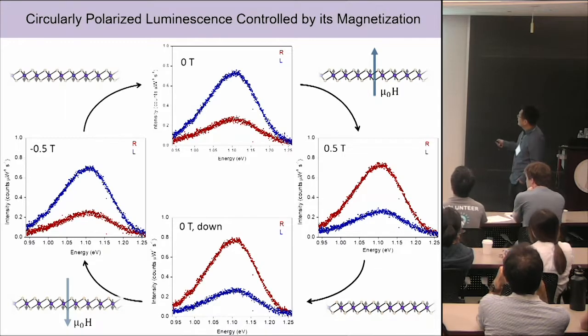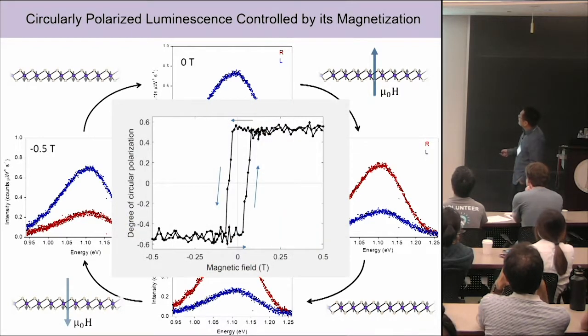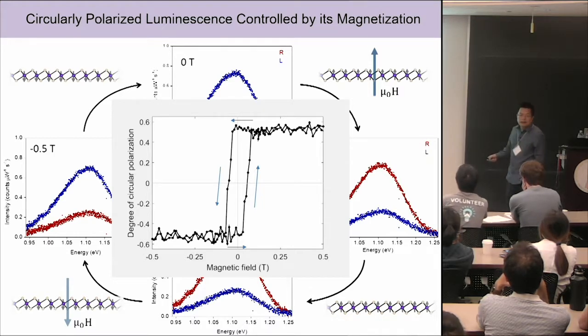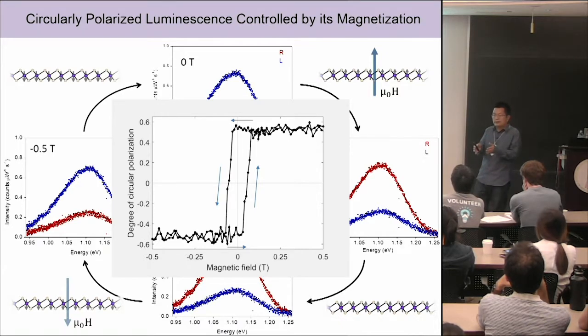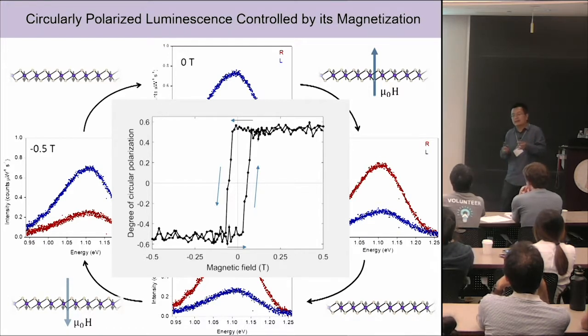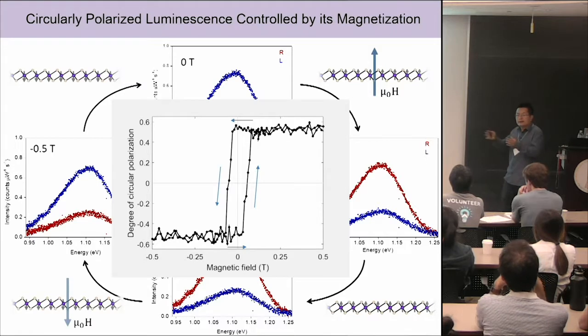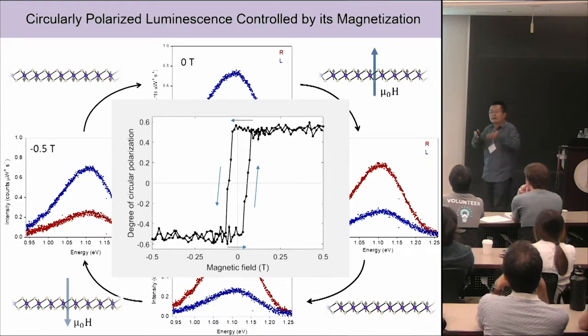So we can plot the degree of polarization as a function of magnetic field, and we see this hysteresis curve here. This hysteresis curve is very different from the MOKE I just told you about. MOKE measures the light scattered from the sample at the same frequency. But what I measure here is luminescence, which is light emitted from the sample itself. But both show this hysteresis, and they point to the same origin of the signal, which is the ferromagnetic order.